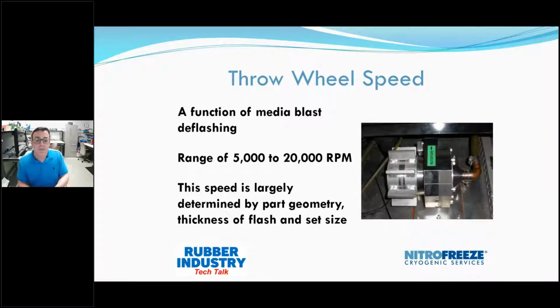Next, we have throw wheel speed. This is a function of media blast deflashing; you're not going to have a throw wheel in your cryogenic tumbler. The throw wheel draws media up from a hopper underneath the cryogenic chamber, pulls it up, and then blasts it out. The speed range is 5,000 to 20,000 RPM, and that can vary machine to machine. With the equipment we use, which is by CDS, that is the range.